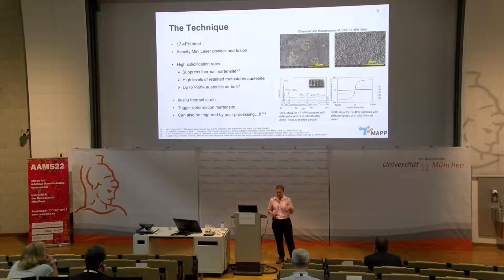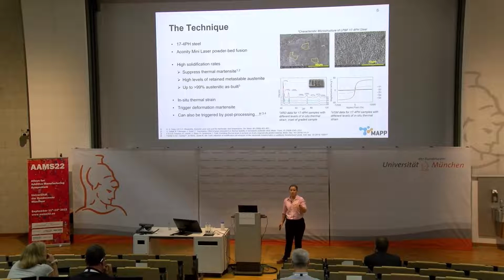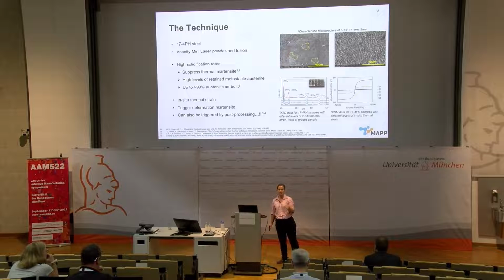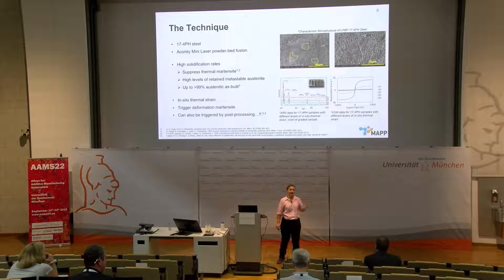One other aspect of this to be aware of is that that deformation transformation can also be triggered by post-processing. So one of the things you may look at in this presentation and go, why hasn't she done EBSD? The reason is, if I polish the surface, I transform my product. So it's one of the challenges that we're actually looking at currently, is how do we characterize these materials when the sample processing itself changes what we're looking at.